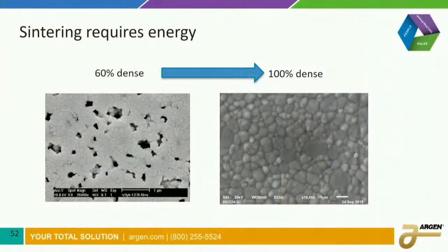Okay. Now, sintering requires energy because we're trying to get from a 60% dense material, that's what the density of that disc is that you're milling, into 100% dense. And remember, zirconia is not like dental porcelain, it's not a glass, it actually is a crystalline material. It's a crystalline material like a metal is a crystal, only the grain boundaries are very weak. But we want to go from 60% dense to 100% dense. What does that mean? We've got to get rid of these air pockets in there.